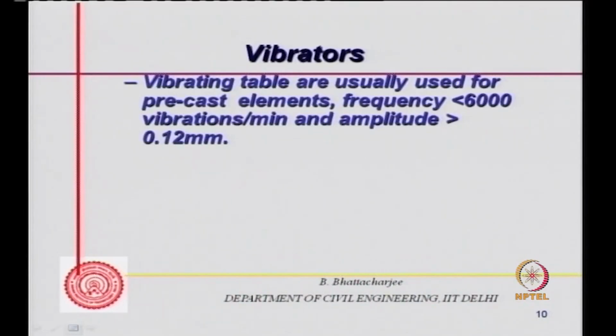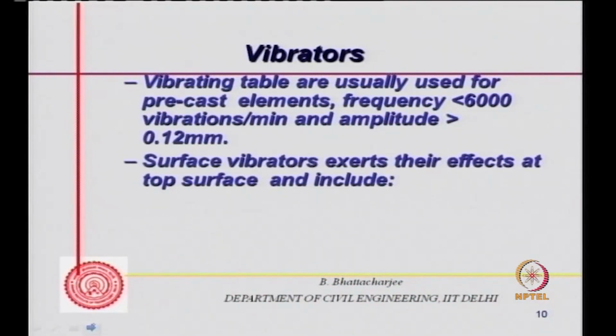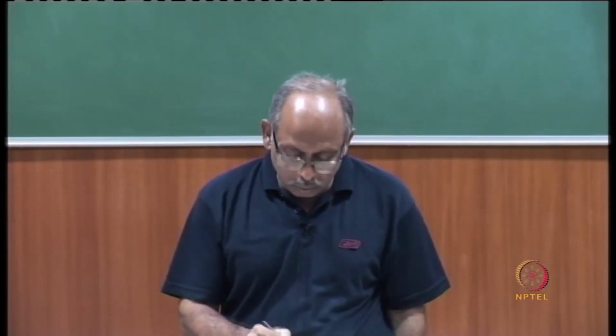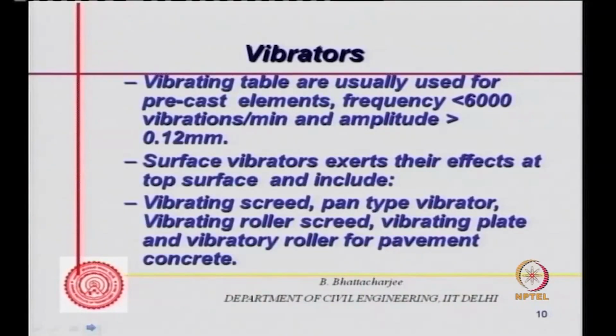The other kind of vibrator, that is table vibrator, vibrating table, is usually used for precast elements or for laboratories. Frequency is less than 6000 vibrations per minute, and amplitude is greater than 0.12 millimeter. So for precast elements, one can use this. Surface vibrators exert their effects at the top surface and include, of course, the vibrating screed, pan type vibrator, vibrating roller screed, vibrating plate, and vibrating roller for pavement concrete. So they have their specific use.